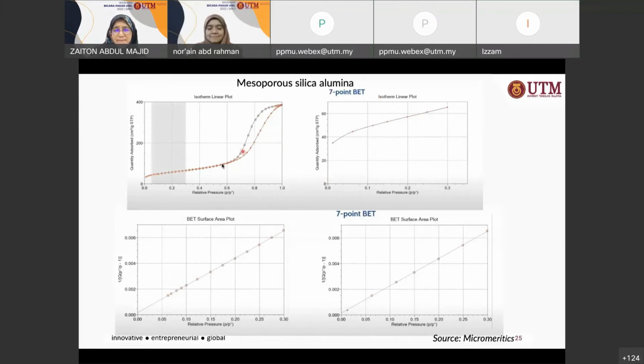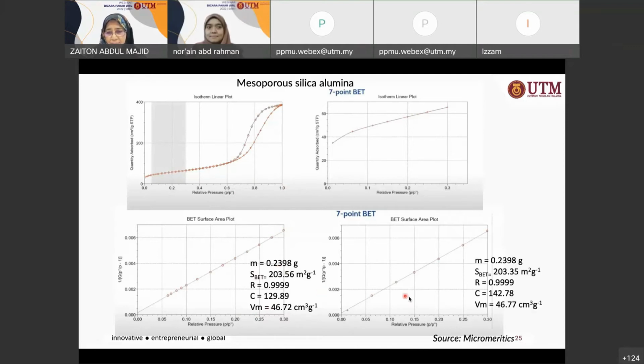This whole thing is the whole isotherm, right? They run the whole isotherm and then they run the BET surface area plot. In another way, they just run a 7-point BET, and from there they get the BET surface area. So if you compare the data, if you run the whole isotherm up to P over P naught relative pressure of about 1, and then do the BET transformation plot, the masses are the same. They use the same mass for both methods, 0.2398 grams.